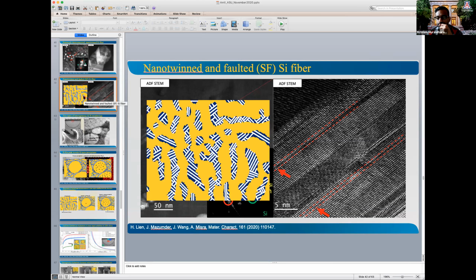This is how the silicon fibers grow from the liquid phase. Twins in silicon have also been seen in nanowires. If you talk to electronic materials people who grow silicon nanowires, they also see them from the vapor phase. Sometimes they grow the nanowires from a gold-silicon eutectic. They have a melt pool and they drag it and grow. So this is just growth twins. What happens under deformation, we don't know yet. We have to see if you get deformation twins or not.